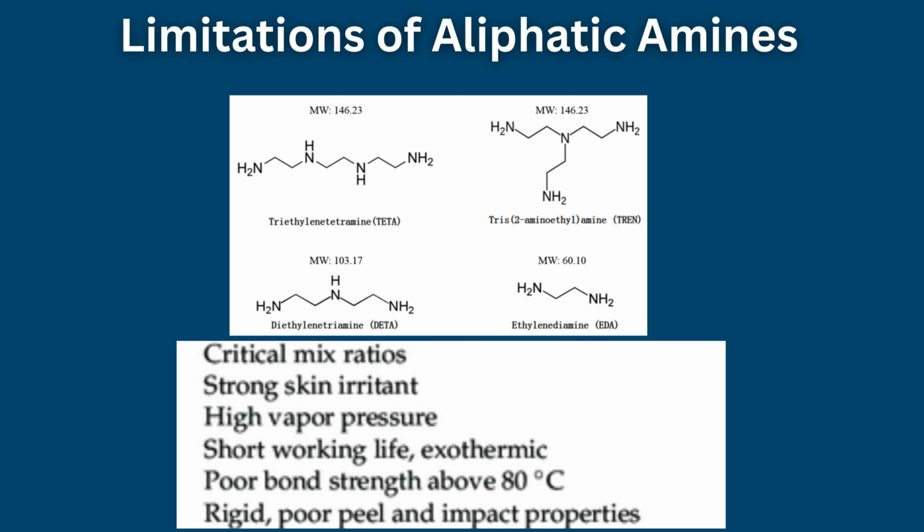Limitations of aliphatic amines. Despite their advantages, aliphatic amines also present several challenges in adhesive formulations. One common issue is the formation of surface blushing, an oily layer that can appear under humid conditions. This phenomenon results from reactions between amine hydrogens and carbon dioxide in the atmosphere. Another problem arises from the high reactivity of these curing agents. Rapid reactions at room temperature can lead to short pot lives, limiting the working time available for mixing and applying the adhesive. The high cross-link density produced by these reactions may also result in brittle materials with limited impact resistance.